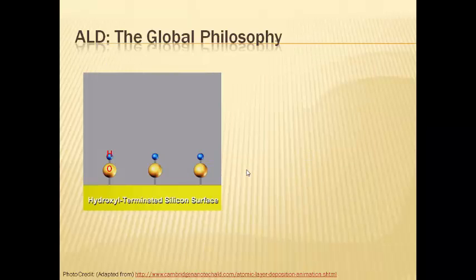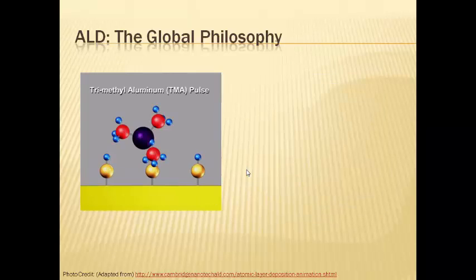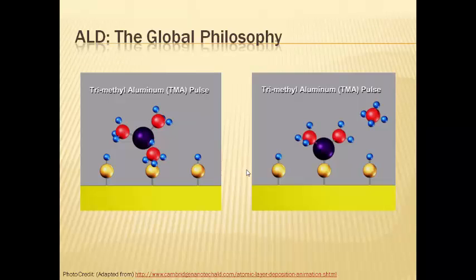Here we come to the more detailed understanding about the controlled monolayer formation process of aluminum oxide. We start with a silicon substrate which is terminated using hydroxyl functional groups. We pulse precursor A which is trimethyl aluminum (TMA). One methyl group of TMA accepts hydrogen from the hydroxyl group. A new bond forms between aluminum and the oxygen of the hydroxyl group, forming dimethyl aluminum oxide while methane forms as a by-product.